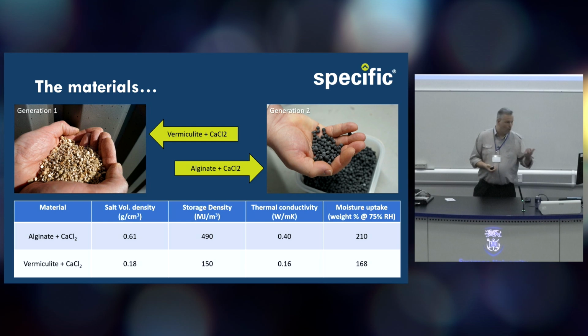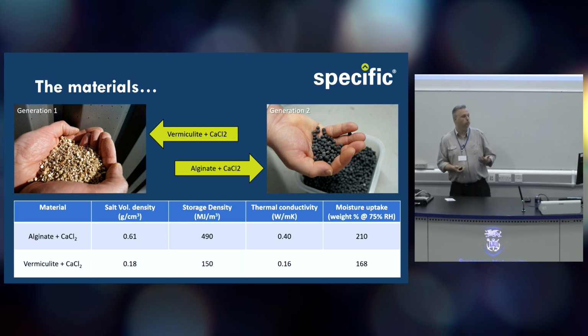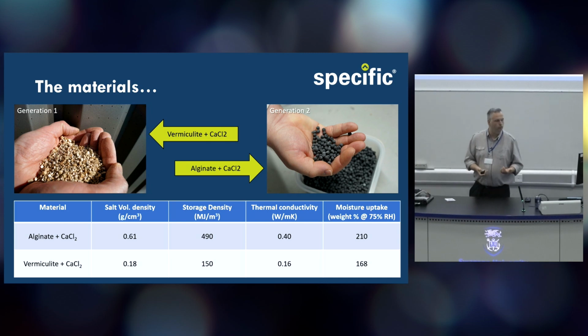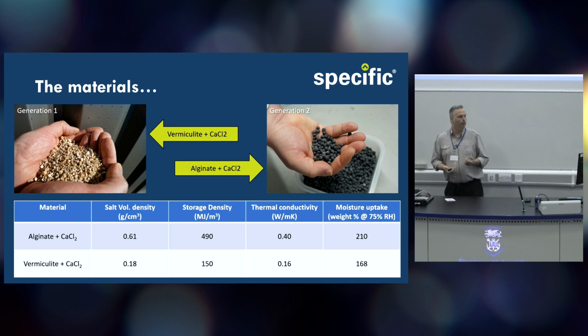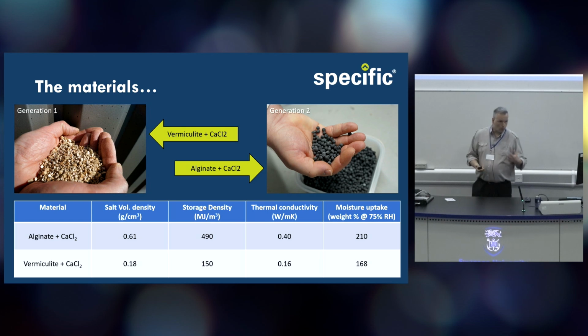What we're trying to do then is improve the energy density and the thermodynamics around the system. So by modifying the matrix, we can increase our energy storage density from about 150 megajoules per cubic meter up to around 490 megajoules per cubic meter. We can also improve the thermal conductivity, so that makes the process a lot more efficient. We can capture more moisture, and if you think back to the demonstration I've just showed you, the moisture is the fuel for the system essentially, so that enables a greater efficiency as well, and we can get more salt into the materials as well.